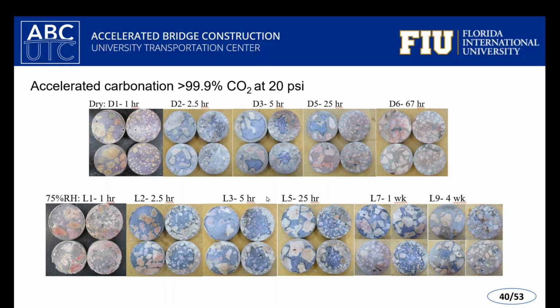With the higher humidity at 75%, we still could carbonate the concrete fairly readily, but it took more time. So in a dry environment, it took about 67 hours to fully carbonate the concrete cylinder. With 75% humidity, it took us about a month. We also placed samples at 85% humidity and soaked in high humidity. In the time period that we were working with these, they did not carbonate, because the carbonation front moves very, very slowly through wet concrete, through the water in the concrete pore water.